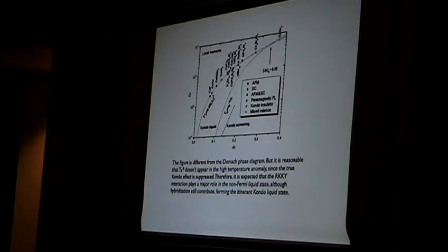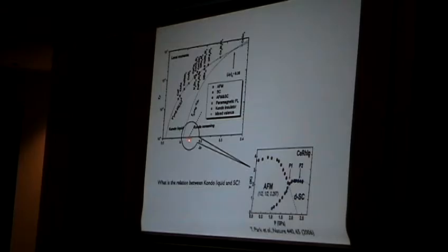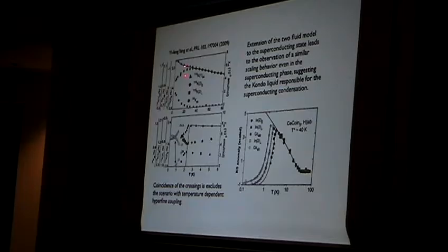Then come back to the phase diagram we have. Below T*, which has universal behavior, we think that's probably some kind of quantum spin liquid. And of course, if the original theory is correct, there will be Kondo screening at very low temperature. This is supposed to be the quantum critical point. Around this quantum critical point we have superconductivity and coexistence of antiferromagnetism.